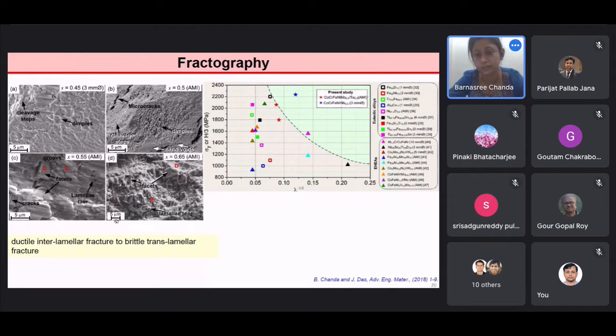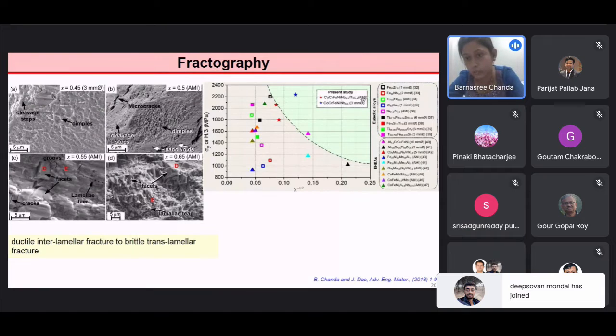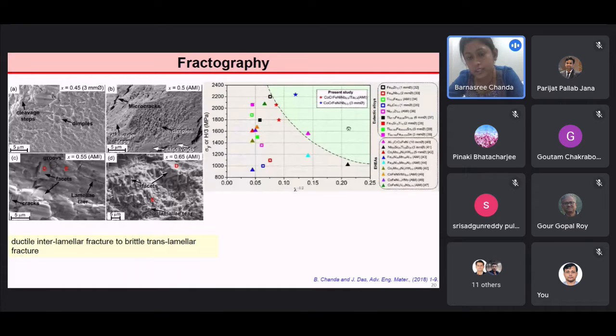We plotted the yield strength versus the inverse of the average eutectic lamellae thickness, where we compare with various binary to high entropy alloys and see that the present eutectic high entropy alloy has excellent yield strength with the corresponding average eutectic lamellar thickness.